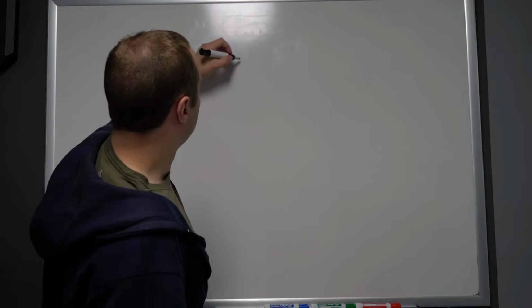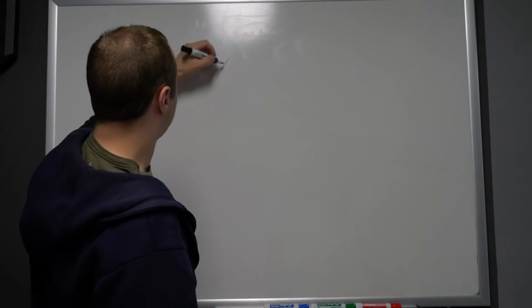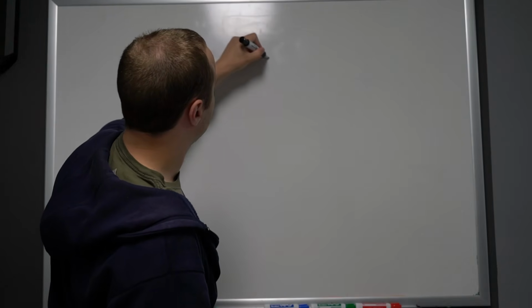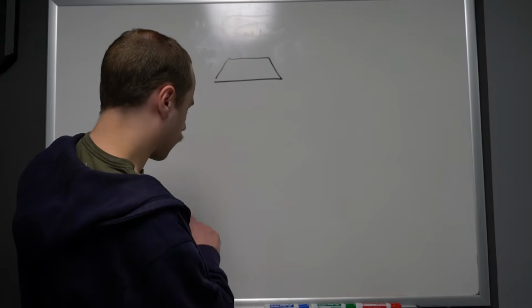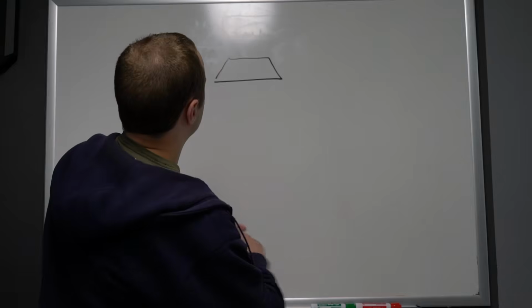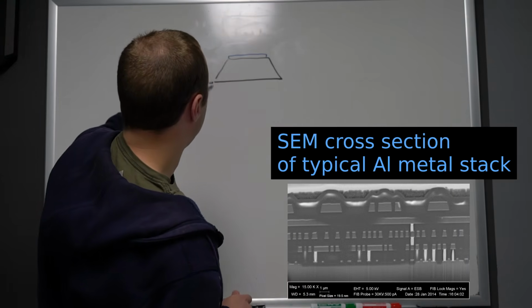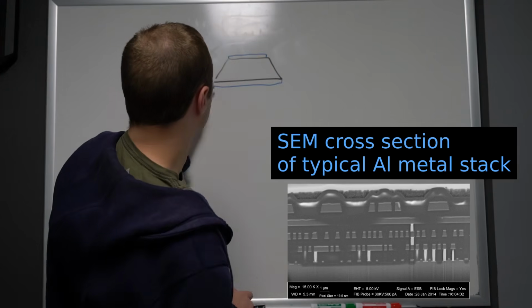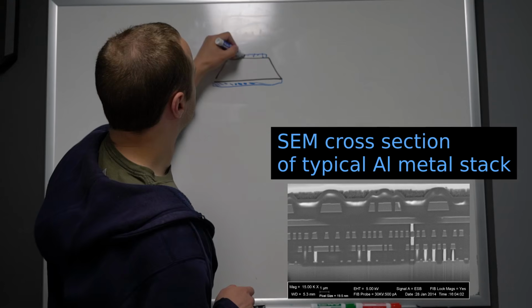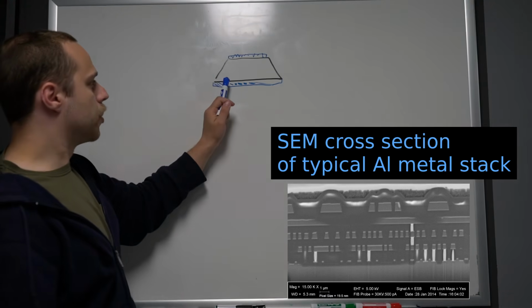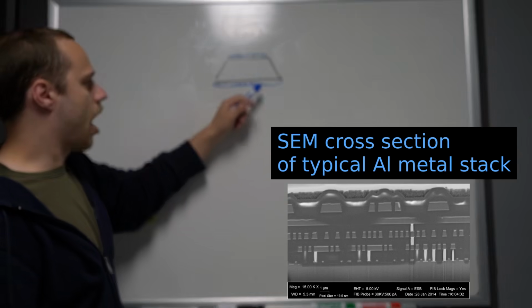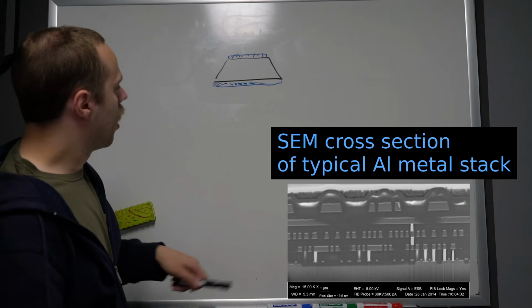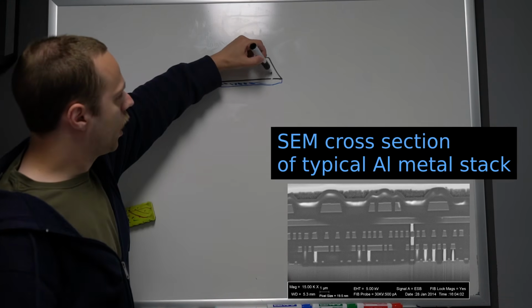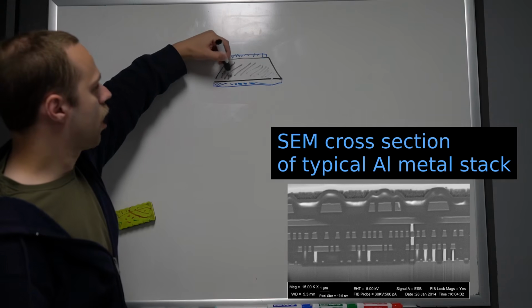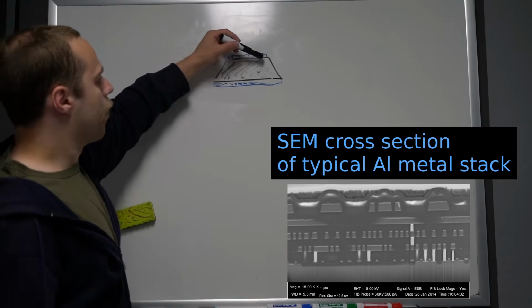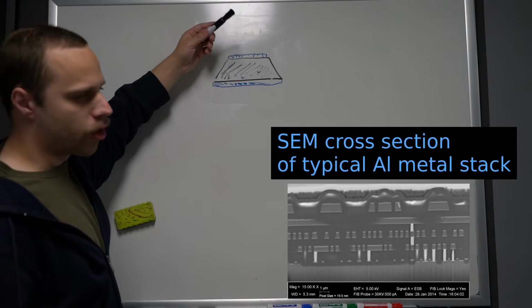And so zooming in a little bit more at the metal layers, what we're actually going to see in cross-section, if we look at each layer, is they're going to look a little bit more like this. And then we're going to have top and bottom cap layers that I'll get to momentarily. I am somewhat exaggerating the slopes and the layer thicknesses just for clarity. And so we're going to have a bottom layer, typically titanium nitride, that is used to stick the aluminum to the surface a little bit more thoroughly so it doesn't float off during etching and such. And then we have the actual aluminum conductor that carries the bulk of the current. And then up top we have another cap layer. This is typically titanium or titanium nitride or some combination thereof.